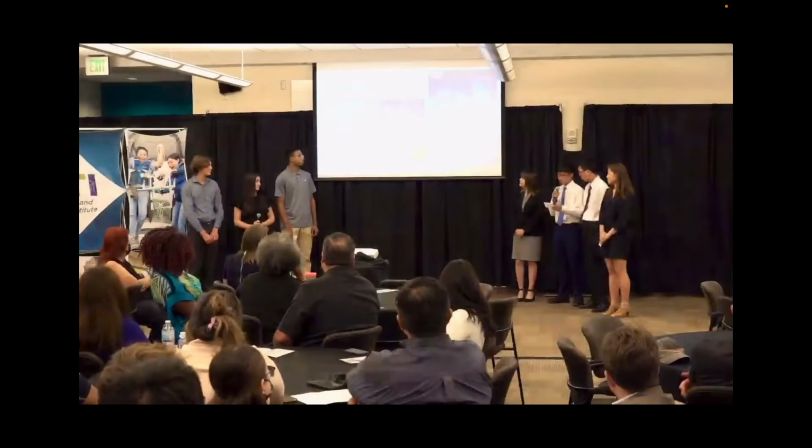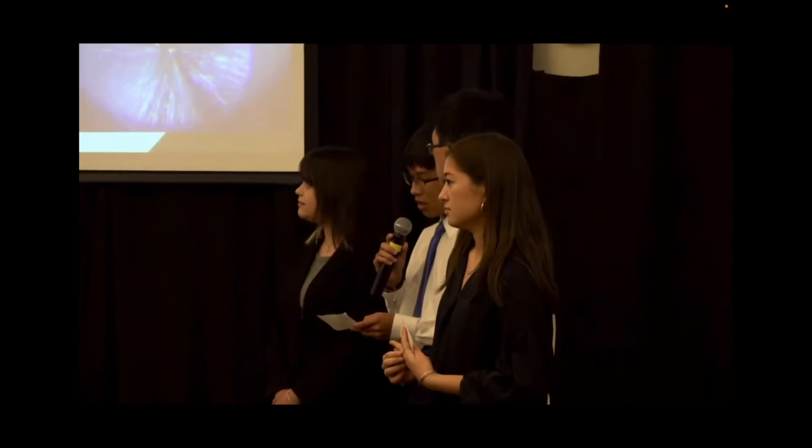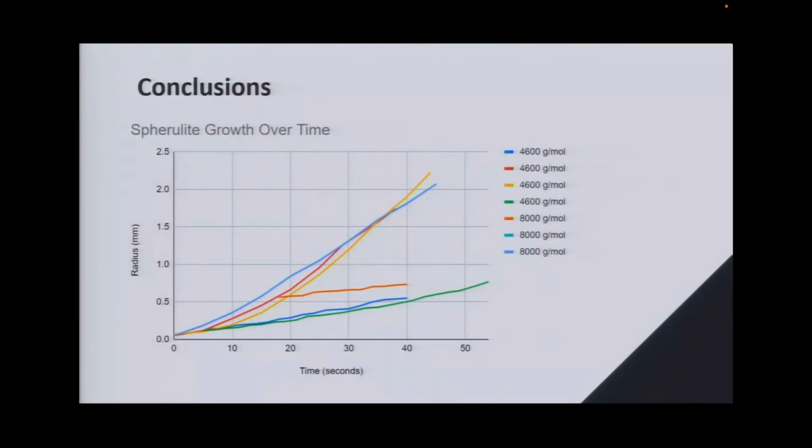We observed quick growth and light refraction in the crystals, as well as a cross pattern which represents a refractive index along a radial and tangential direction. Additionally, we noticed that the spherulite growth rate depended on nucleation and crystal growth rate.